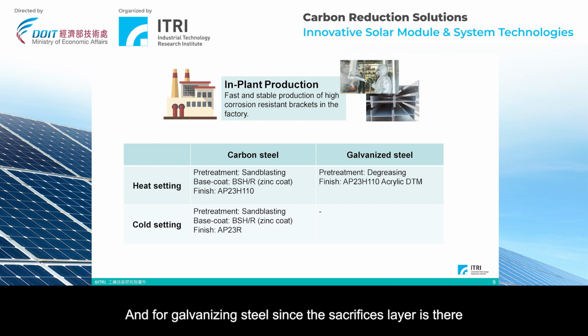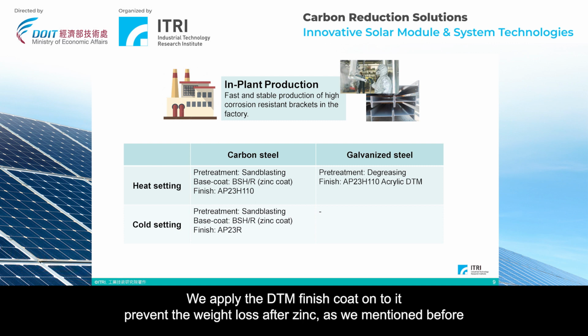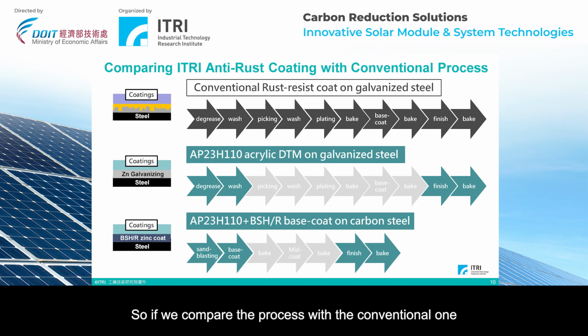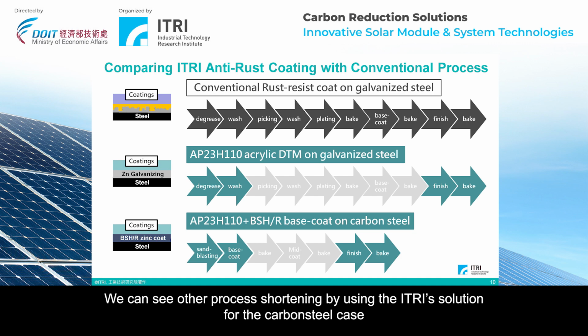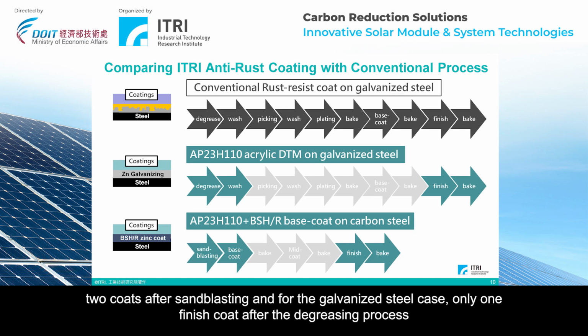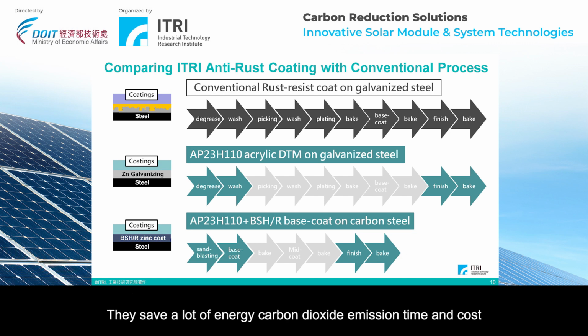And for galvanized steel, since the sacrificing layer is there, which is the zinc or magnesium aluminum alloy, we apply the DTM finish coat onto it, to prevent the weight loss of the zinc, as we mentioned before. If we compare the process with the conventional one, we can see obvious process shortening by using the ITRI's solution. For the carbon steel case, 2 coats after sandblasting, and for the galvanized steel case, only 1 finish coat after the degreasing process. This saves a lot of energy, carbon dioxide emission, time, and cost.